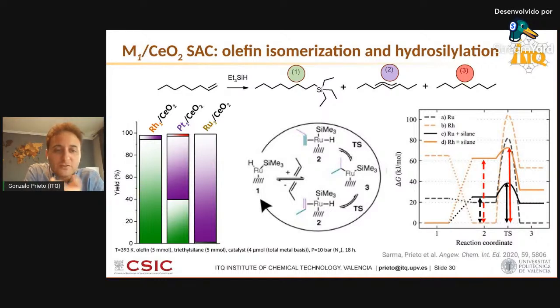But we were very happy to see that a rhodium-based single-atom catalyst was extremely selective to the anti-Markovnikov hydrosilylation of the terminal olefin to produce the terminal organosilane with very little olefin isomerization. And on the contrary, we were also quite surprised to see that ruthenium was very selective to perform olefin double bond migration, isomerization, was inactive, was not capable of inserting silicon. It was not capable of running hydrosilylation.